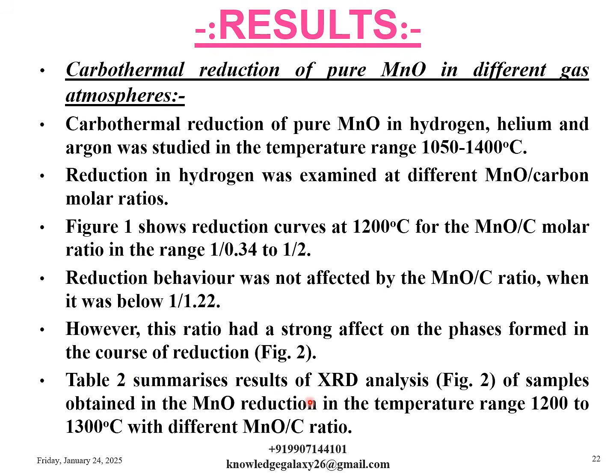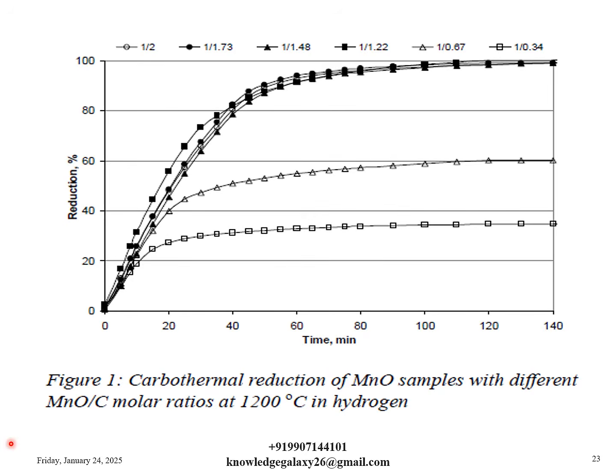Table 2 summarizes the results of XRD analysis in figure 2 of samples obtained in the MnO reduction in the temperature range of 1200 to 1300 degrees Celsius with different MnO by C ratios. So this is figure 1 which describes carbothermal reduction of MnO samples with different MnO by C molar ratios at 1200 degrees Celsius in hydrogen. You can pause the video and observe the figure contents.